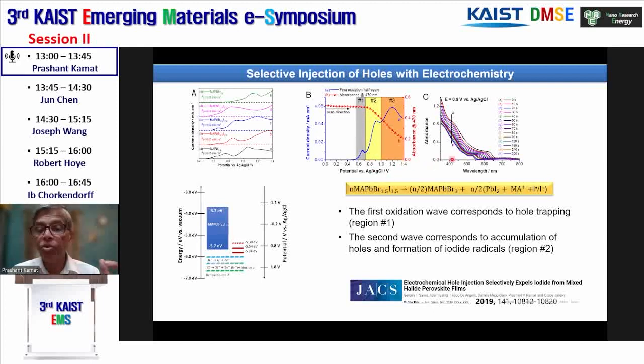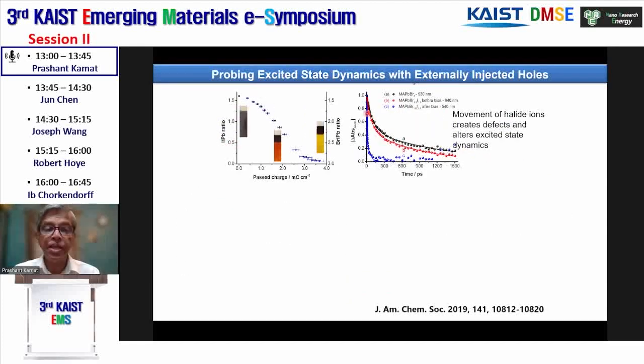This is the region where you accumulate holes in the valence band when you apply about 0.8, 0.9 volts. And we applied that voltage and saw very similar behavior to what we saw in photo irradiation, that is expulsion of iodide into the solution, and it leaves bromide. So all the iodide comes out, leaving behind bromide. And you can picture this through these actual photographs. This is what we start off with, mixed halide, and then it becomes an intermediate state, and then finally it ends up with the bromide in this one.